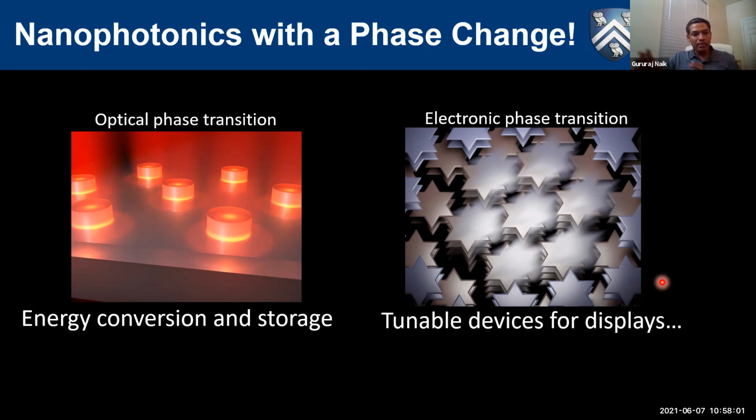So what we did was we put this in a microscope, and instead of doing regular spectroscopic imaging, we turned it into a Fourier imaging spectroscopic microscope. We had to do Fourier filtering as well to choose particular angles and thereby get the angle-resolved spectrum from my sample, both reflectance and transmittance. From that, we were able to extract epsilon in-plane and epsilon out-of-plane, the C-axis and the in-plane axis. So that was the characterization.